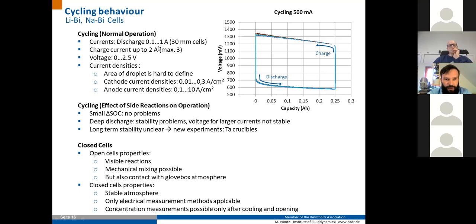For the large cells, we had discharge currents typically of 1 ampere, sometimes higher. Voltages varied between 0 and 2.5 volts. For charging, 2.5 volts means you have some side reaction occurring already during charging the cells. And as I said, the surface area is quite hard to define because the lithium floats on top of the electrolyte and forms quite complicated surfaces between the liquid lithium and the electrolyte, and therefore typical current densities are a bit hard to transfer to, for example, numerical simulations.